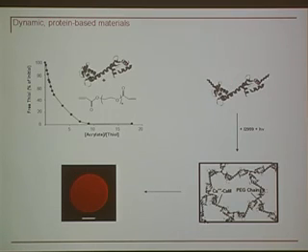And if we then expose this molecule to UV radiation in the presence of a photoinitiator, I-2959, we end up with a three-dimensional network. What you're seeing on the lower left here is a gel that was formed and then stained for protein content. And what you're seeing is the top view of a cylindrical hydrogel that's in solution. So you can see that there's no label that's diffusing out over time. The gel has got protein linked within it, and the protein isn't diffusing out.